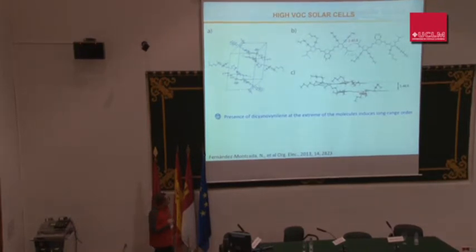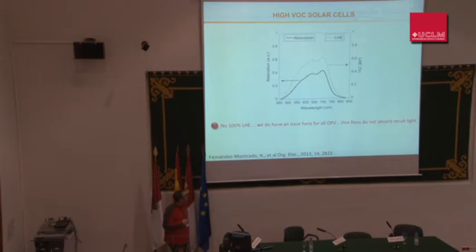It turns out that for this molecule, this is the crystal structure. This is not modeling, this is actually the crystal structure of the molecule. They do not have very strong pi-pi stacking. What they have are hydrogen bonds at the cyanos, and that induces a long range order in the crystal. So you can have very good mobilities because of this arrangement of molecules thanks to the hydrogen bonding, the kind of thing you learn when you study supramolecular chemistry, and that induces very long range order, which is rather important. The problem of these molecules is that you can only make very thin films.